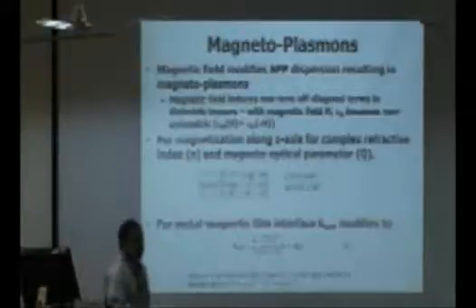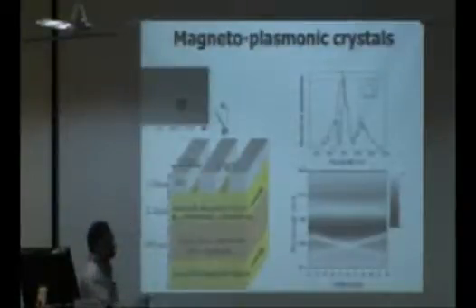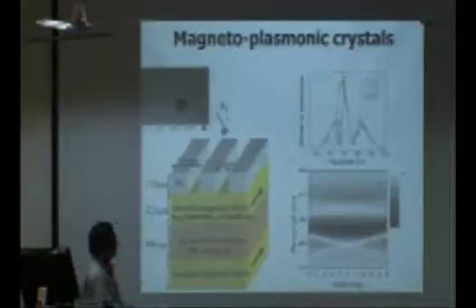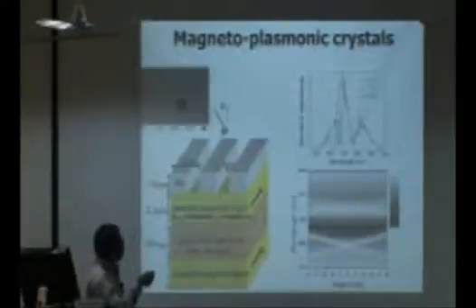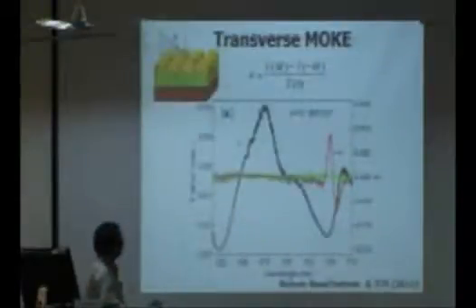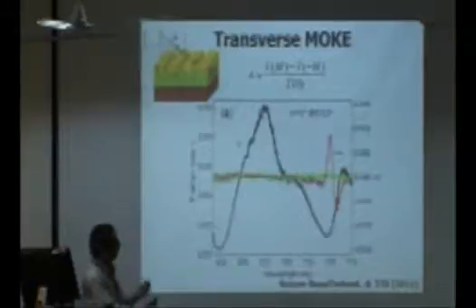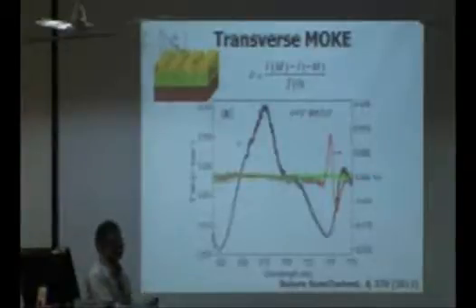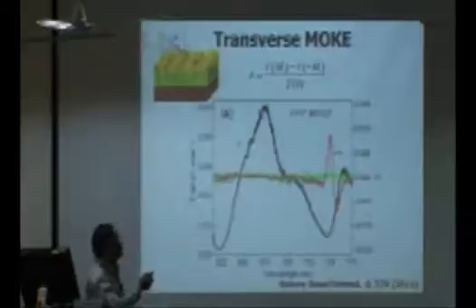Basically the off-diagonal components in the dielectric tensor are getting modified by the applied magnetic field. So what we showed is that we can couple these plasmon modes to the absorption spectrum in magnetic thin films, for example bismuth-doped yttrium iron garnets. By careful design and fabrication, we showed that the calculated and measured dispersion for the plasmons match pretty well, and then we measured the transverse magneto-optical Kerr effect for the first time in transmission geometry. The conventional wisdom is that the Kerr effect is always in the reflection geometry and the Faraday effect is in the transmission geometry. But we showed that the Kerr effect can also be measured in the transmission geometry.